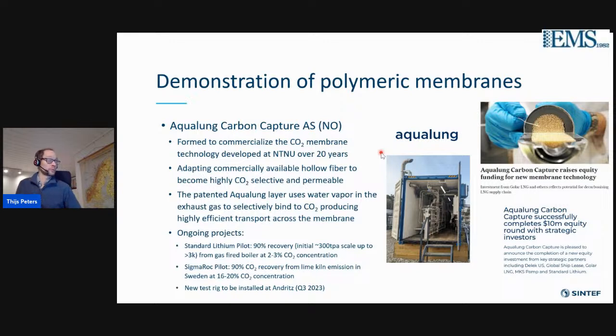It's a company that was established 2 to 3 years ago, but they are rapidly commercializing, but also building their knowledge further. And they have many different projects going on. For example, a standard lithium pilot in the US, where 90% recovery of the CO2 is efficient, and initially 300 ton per annum of CO2 is being captured, which is going to be upscaled to 3,000 ton per annum CO2 capture from a gas-fired boiler with only a limited CO2 concentration of 2 to 3%.